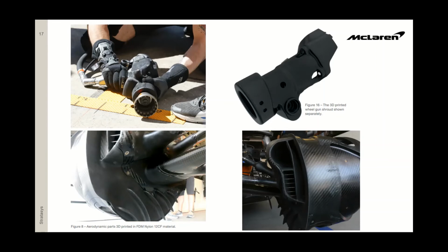When you look at other technologies out there from FFF, for example, like Markforged, where they've got an Onyx material, which is a nylon 6 with 15% carbon fiber, they have to use the continuous strands to reinforce the material to get the same stiffness. They are very strong on the continuous fiber, but basically when we print solid, we get almost the same mechanical performance, but you do have 4 times the build speed. You don't have the same issues when printing the models.